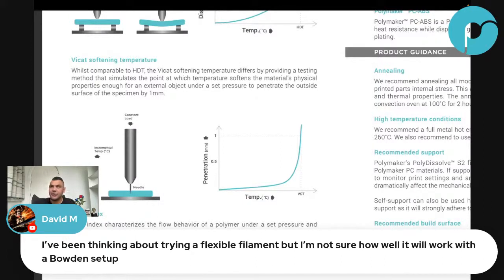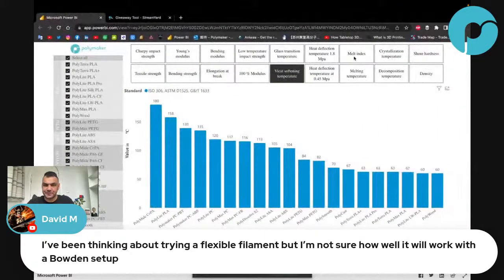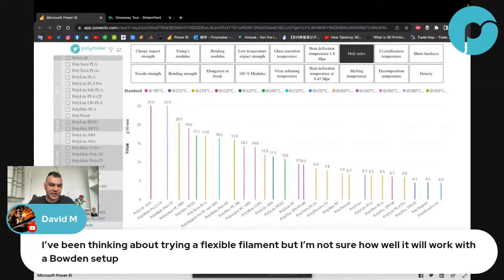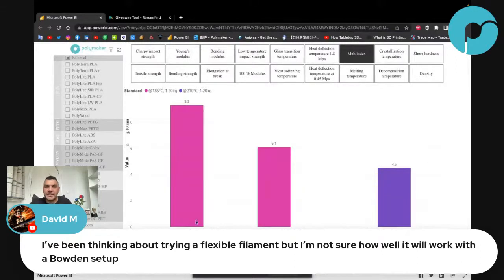And that's why we have created TPU HF, high flow. High flow means the melt index of that TPU is very high, which means it won't require as much pressure to be extruded. If you go and check the melt index, let's check our TPU. Okay, so you can see the HF here. This is regular TPU 95. For regular TPU 95, the melt index is 4.5 at 210 degrees.